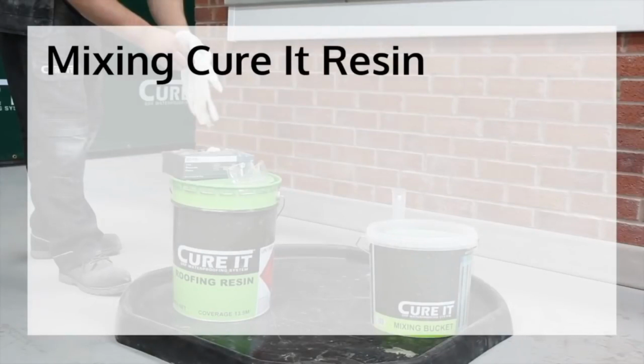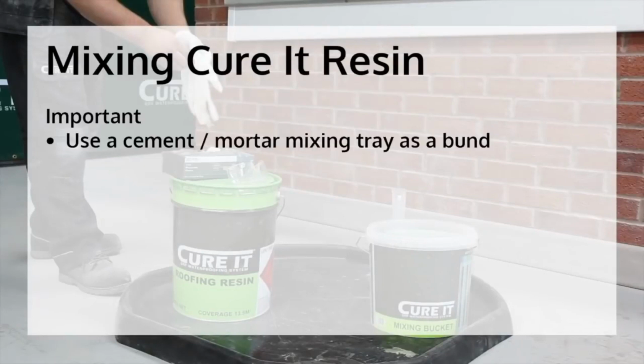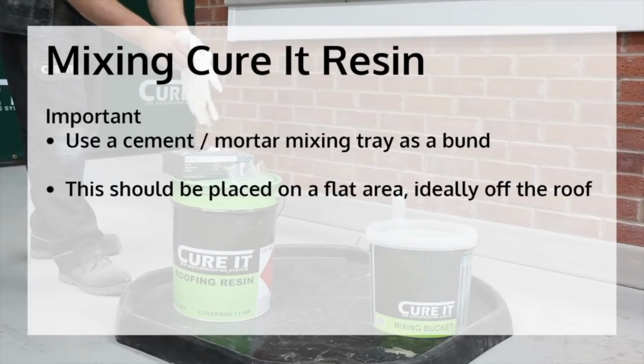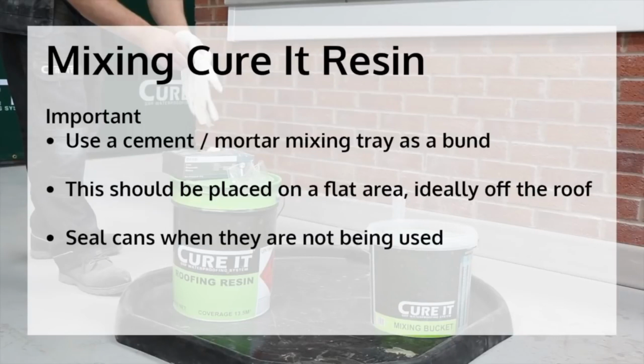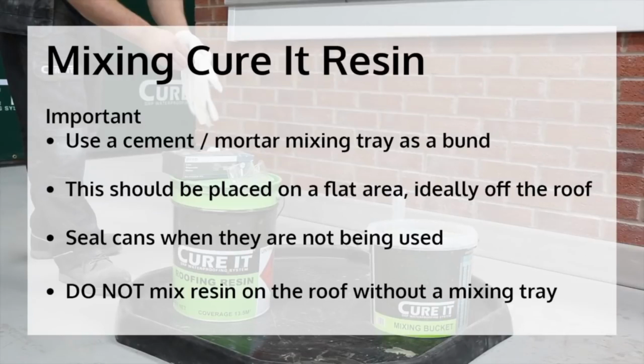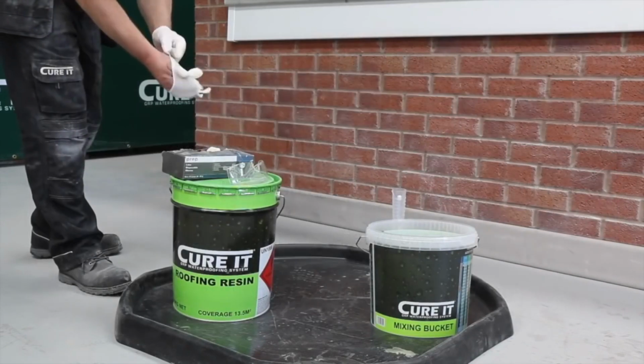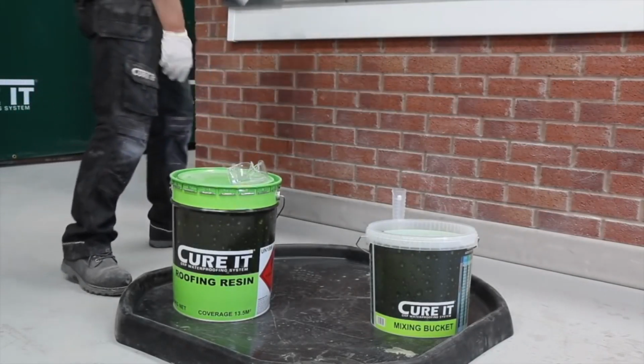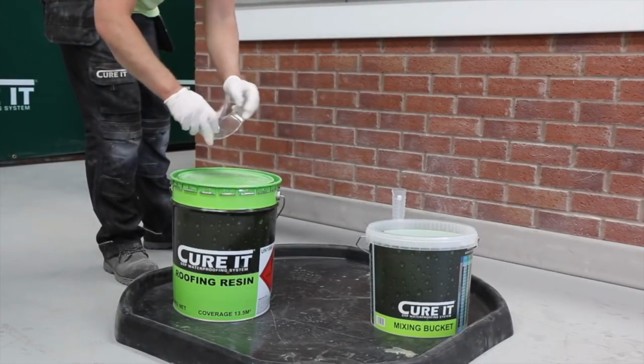The next stage of the process is the mixing stage. Use a cement mortar mixing tray as a bund for decanting and mixing of resin and top coat on the roof. This should be placed on a flat area, ideally off the roof if possible. Seal cans when they are not being used. Do not mix resin on the roof without a mixing tray. Uncatalyzed resin spilt on the roof can generate an odor which can be almost impossible to resolve.